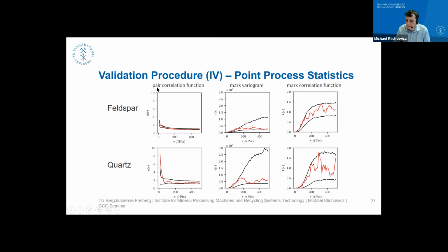So I have here the results for feldspar and quartz, so the two phases with the highest proportion in the microstructure. And the first measure is the pair correlation function, g(r). And what we see here is on the x-axis, we have the radius r. That's the radius of our field of interest that starts in the middle on the grain where we're just looking, and increases with a higher radius.